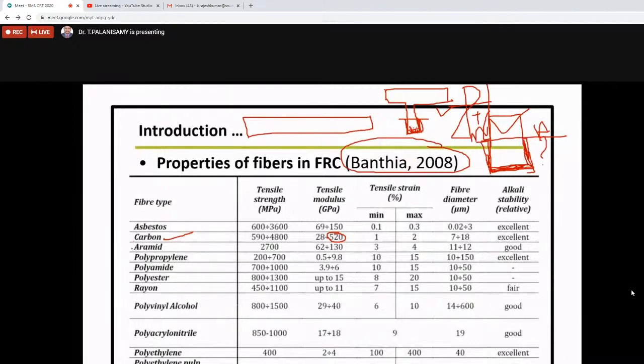And also aramid fiber, this also we did. The problem is that it absorbs a larger amount of water. We tried it. But whenever we need dry concrete, it may be placed in wet places, and we can go for the aramid fiber because the tensile strength is good, nearly about 2700 MPa. The tensile modulus is also like that. Then we come to the polypropylene fiber also.